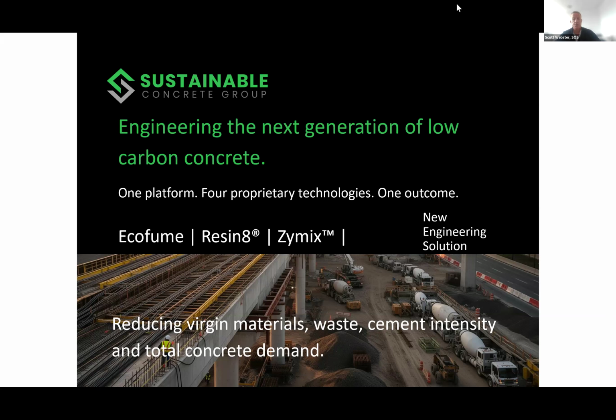So we have those two products, as well as Zymix, which is a new product coming to market at the moment, which has also been certified by Boral. It is a cement additive that reduces the volume of cement needed to achieve the desired MPa mix. That reduction is as much as 15 to 20% of cement needed. And it works exceptionally well with slag and also calcined clay, which we were just talking about a moment ago.